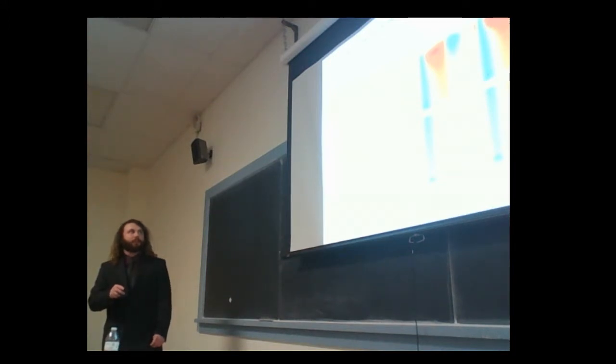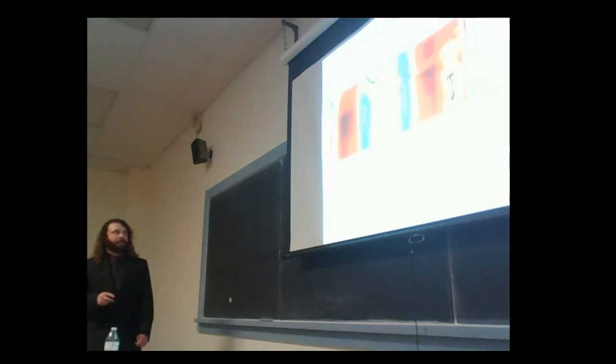And so at room temperature, this is the normal phase response, so this red curve, and then this blue curve is at 3 Kelvin, and this is the charge density wave phase. Here's the 550 and the 690 nanometer optical signature of the charge density wave. And this is also the decay associated spectra for the nanosecond decay at different temperatures. So with this information in mind, there's an experiment where I use low fluence measurements for pure titanium diselenide.